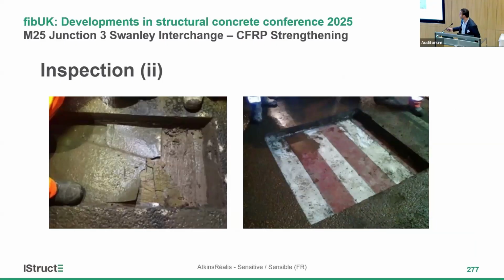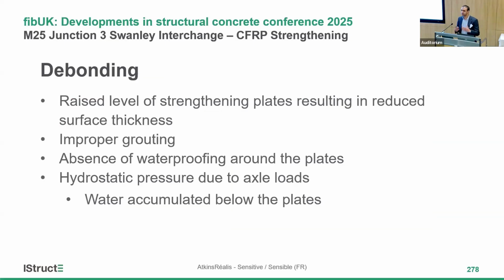Here on the left image, you can see the waterproofing layer peeling off from the surface, and this is the infill mortar next to the steel plates, which is having issues. So the exact reason of this debonding is not confirmed, but we suspect all this has contributed to it, which is the raised level of strengthening when the steel plates are installed on top of the concrete deck, which reduces the surface thickness. Improper grouting, as we saw in one of the images. Then absence of waterproofing around the plates, and also the hydrostatic pressure of the axle loads, which keeps accumulating on top of the steel plates. So all these are the reasons for debonding.